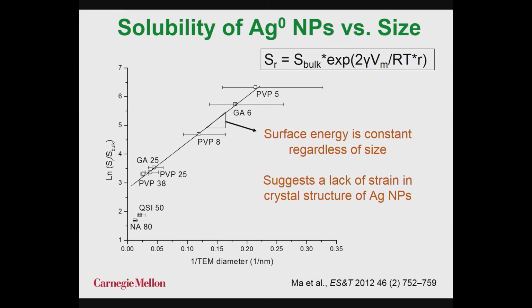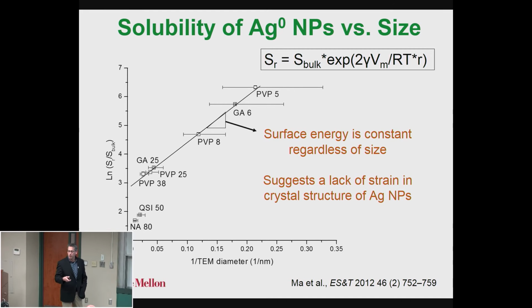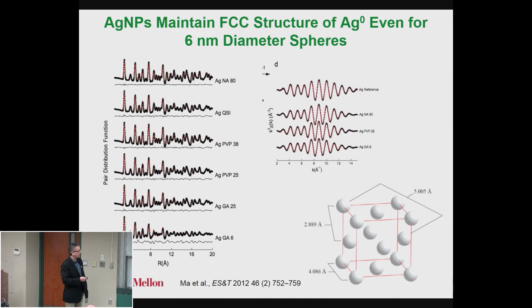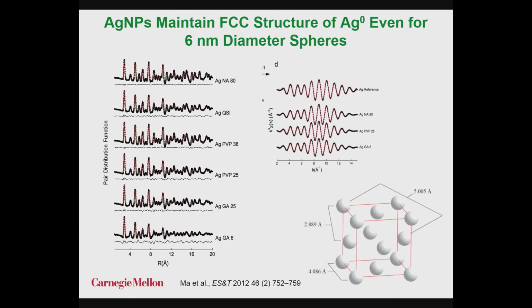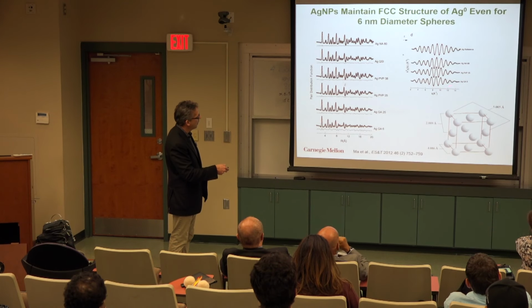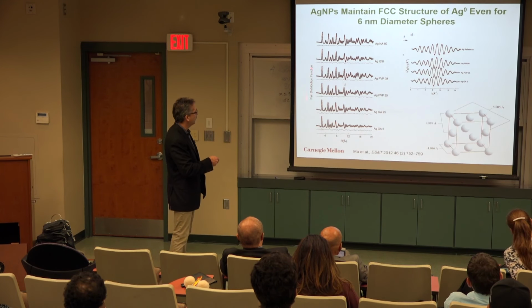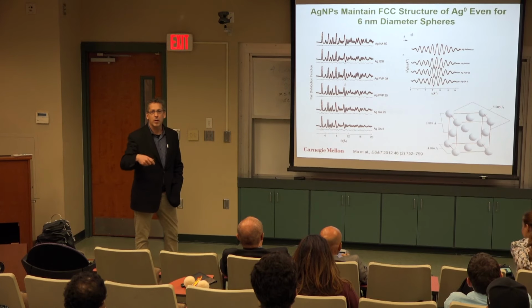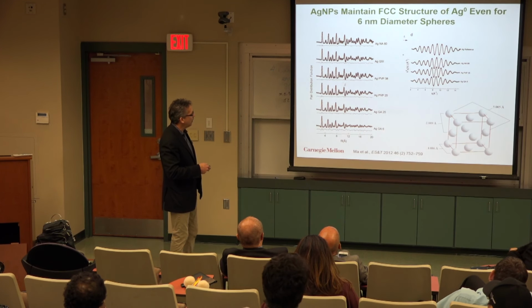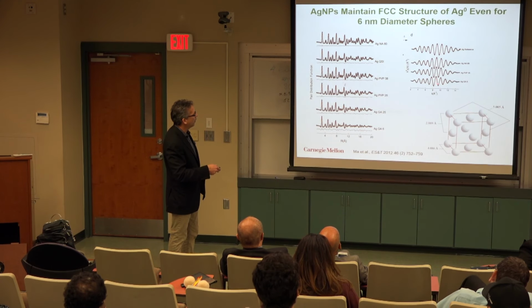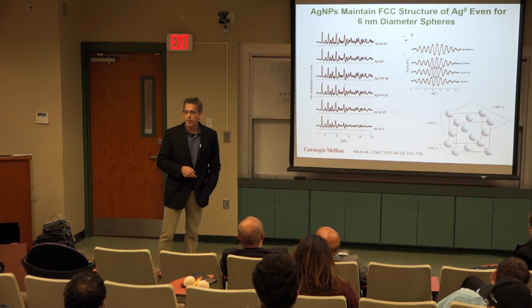Okay, but this wasn't good enough. We could speculate that. So we said, okay, what can we do with X-ray to figure that out? So we went and did a couple of things. We do X-ray absorption spectroscopy, and these are the spectra you get, and these are different size materials. And we also did pair distribution function analysis, which is sort of total X-ray scattering that we also do on the synchrotron. And you don't have to be an expert to look at these and say, there's no difference.